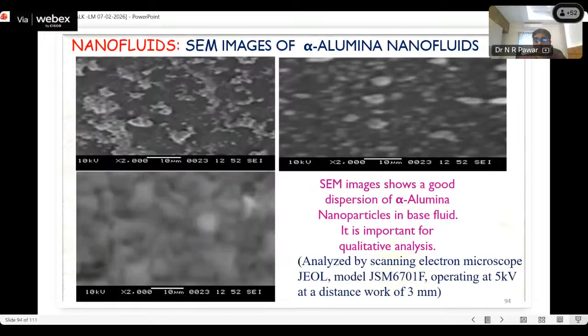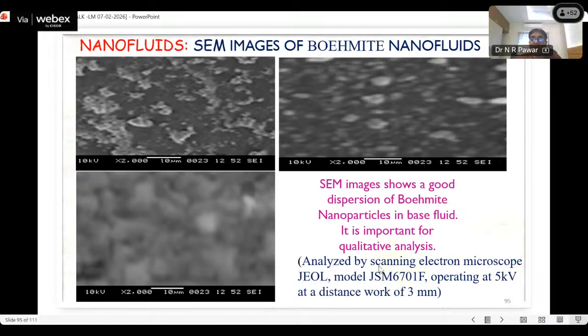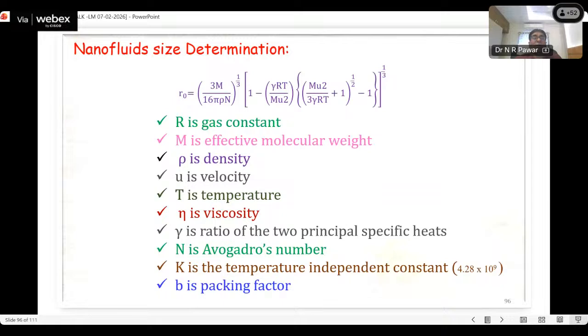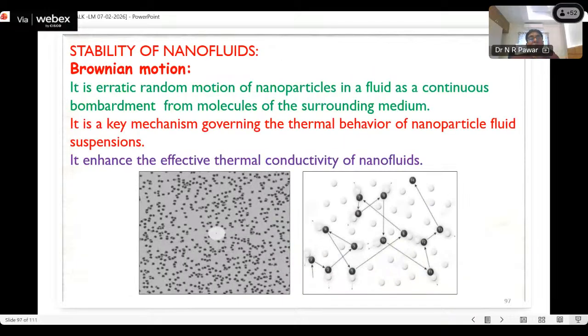And for that we use the two-step method, and these are some SEM images of the alpha alumina nanofluid, and definitely these images are completely different from the SEM images of these nanomaterials. SEM images show the good dispersion of alpha alumina nanoparticles in the base fluid. It is important for the qualitative analysis. We measure this by using these SEM images of boehmite nanoparticles. Also, by using this formula, we may find the size determination, and it is also observed that the size of the dispersed materials in the base fluid is different from their original size, and hence we conclude that the synthesized nanoparticle is excellent for the synthesis of the nanofluid.